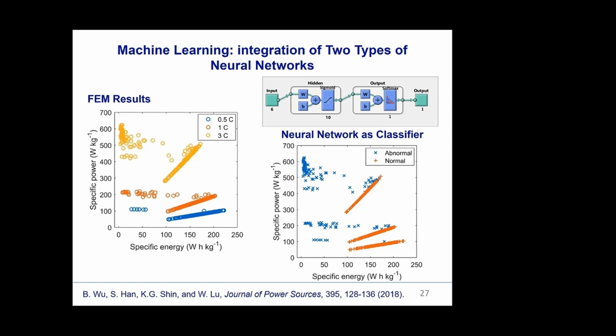The figure on the left shows finite element simulations of specific energy and specific power for various combinations of parameters. We can observe that some results seem to show a trend, such as the lines, while some others seem to be random, giving very small specific energy. Upon further investigation, we found that these low specific energy values are due to electrolyte dry out.